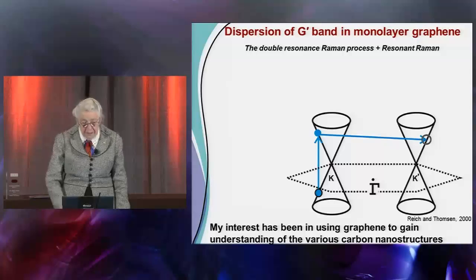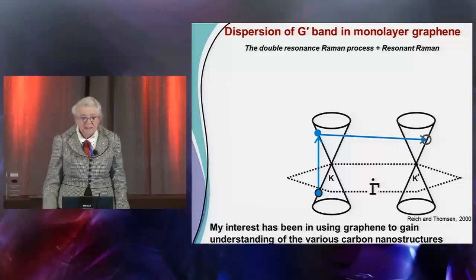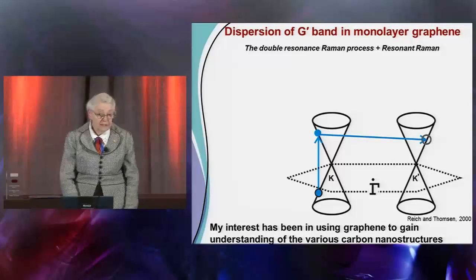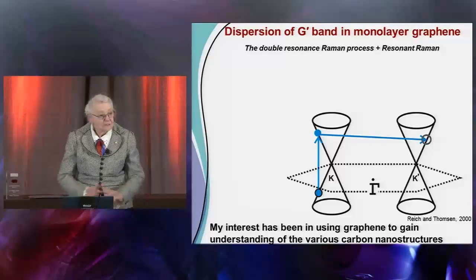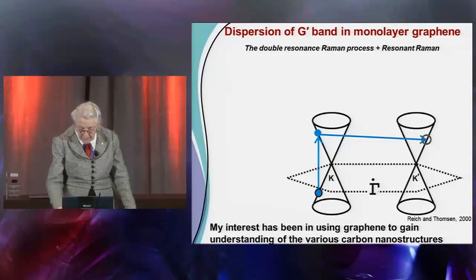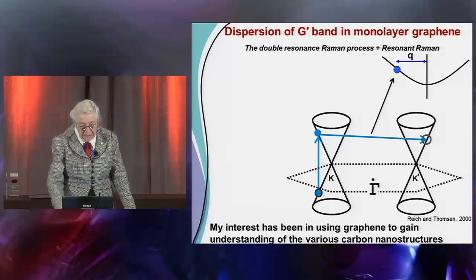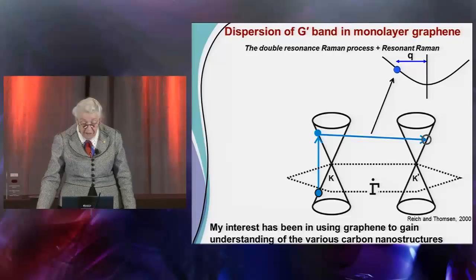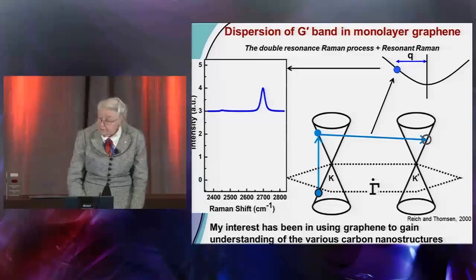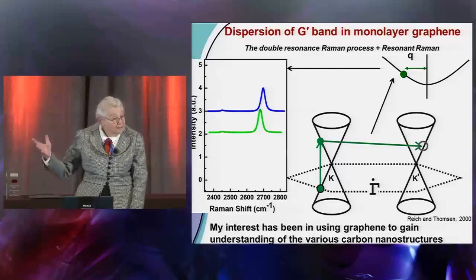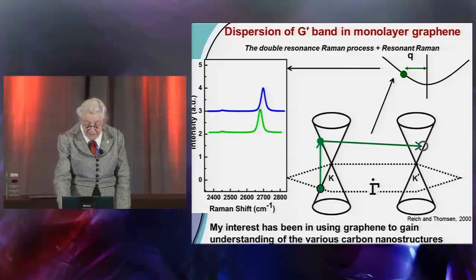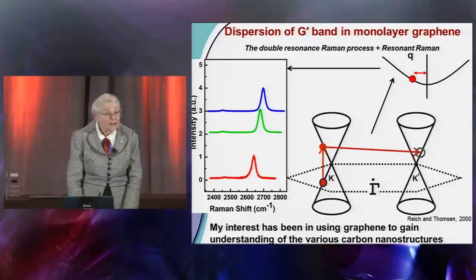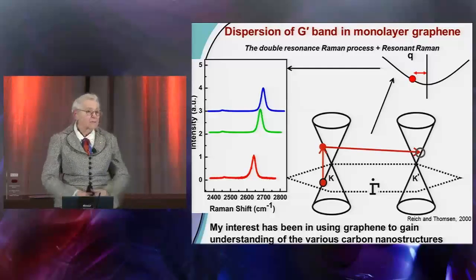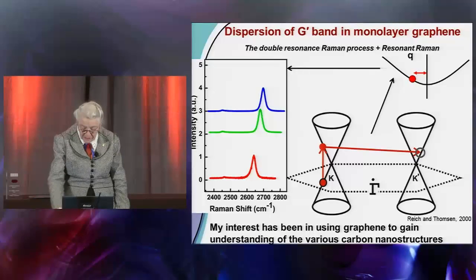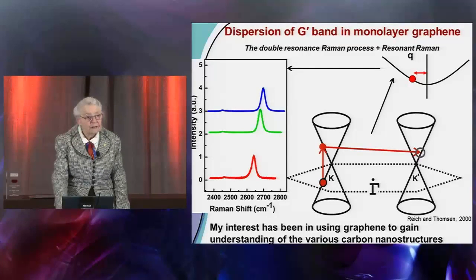And one thing that's nice about a carbon system and the simplicity of it is that you can study wave vector-dependent phenomena. There's very few systems that you can really do this quantitatively. So with spectroscopy, this can be done. And so you excite this wave vector, Q, blue, and then with a different laser energy for excitation, you can get totally different resonance, but also different wave vector. And so this allows you wave vector control and control of phenomena that have to do with wave vectors. So this has been a very interesting part of the nanostructures.